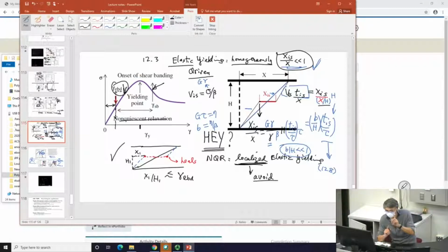So you do the same startup shear. If you're willing to do it as if it's a continuous shear, so you just watch with your movie, you'll find the sample could break up after the overshoot point, the shear banding, which is the subject of chapter 9. Chapter 12 is about terminating that startup shear even before the yield point. So you terminate it, for example, beyond the threshold, anywhere here, and you find after termination, the sample would break up.